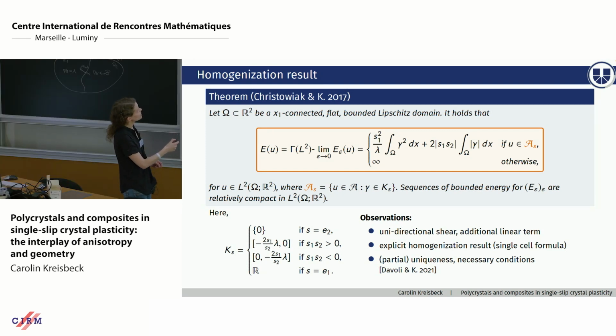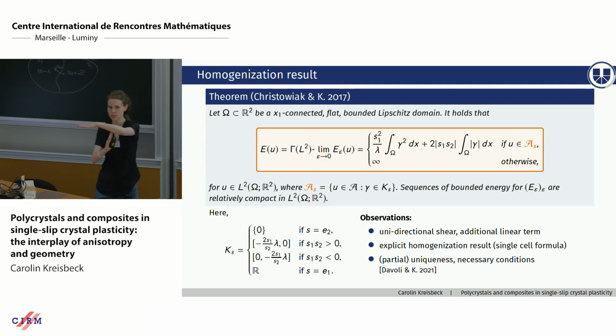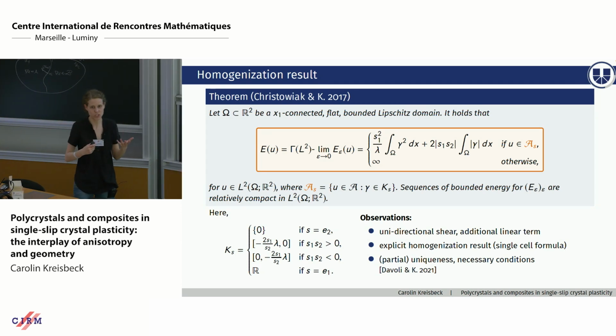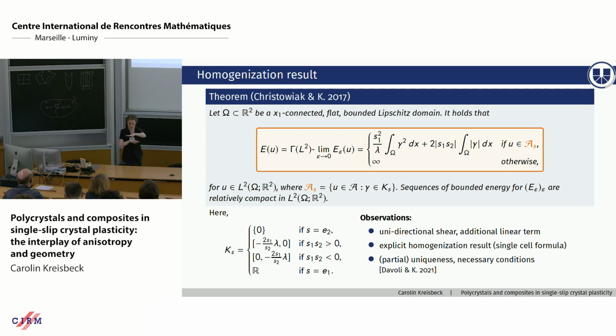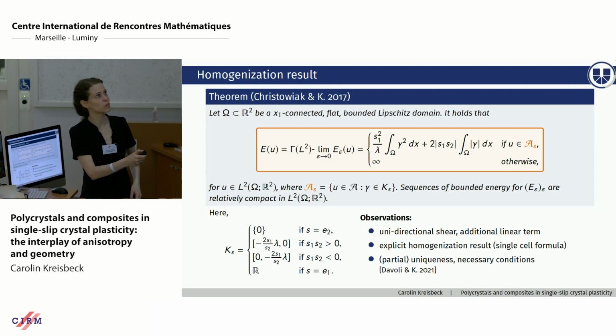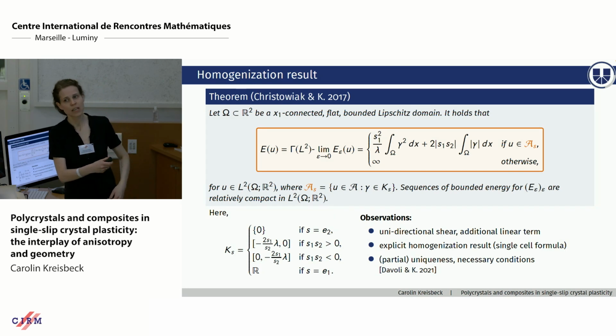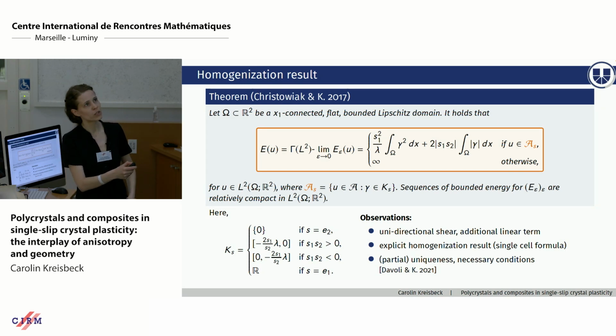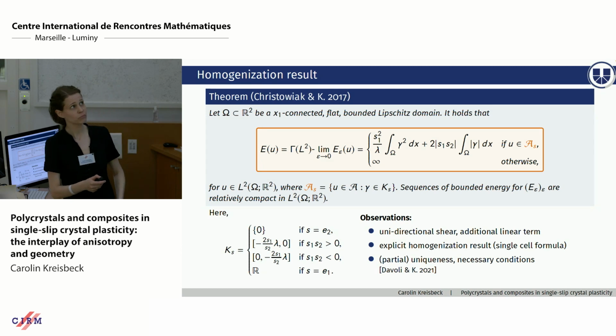So in the case that S is E2, the slip system is orthogonal to the layer, so the intuition is that it would get blocked, and this is exactly what we see here. So no slip is possible at all. In the other case, when the slip system is parallel to the layers, you would say, yeah, it's free to go, and this is what's reflected here, so no restrictions. And in all the other cases, we get some unidirectional shearing.